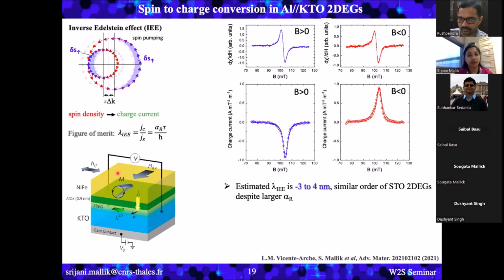So basically at the resonance, a spin current from the permalloy got injected in the 2DEG layer. And due to the inverse Edelstein effect, a charge current got generated perpendicular to the spin current direction. And then we could measure the corresponding voltage due to this charge current. And when we did this, we found a really nice symmetric signal exactly appearing at the magnetic resonance. And as we change the polarity of the magnetic field, we can see that the sign of this charge current also changes. So this is also something we wanted for the MESO device.